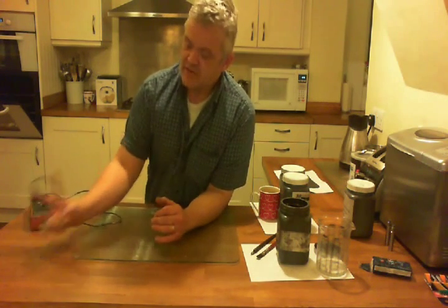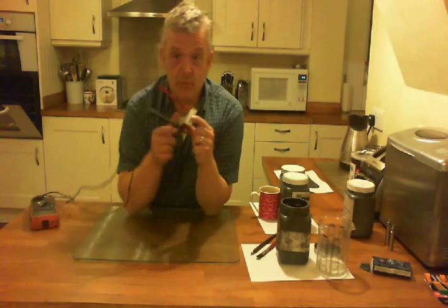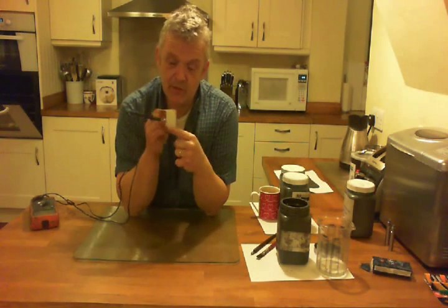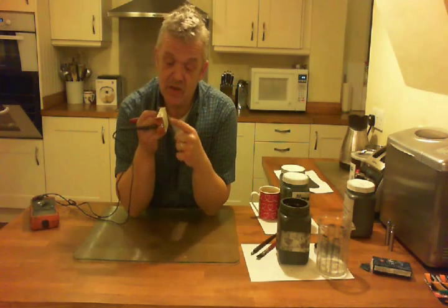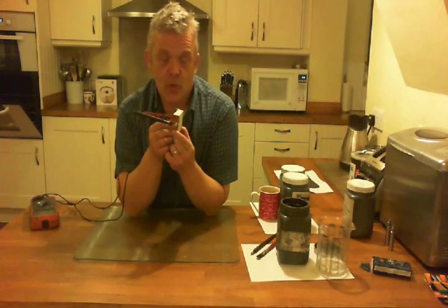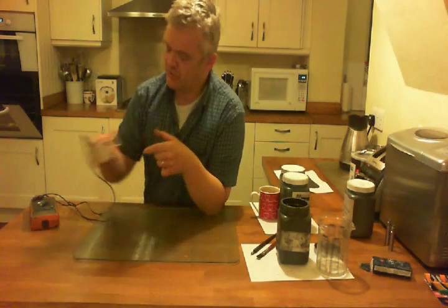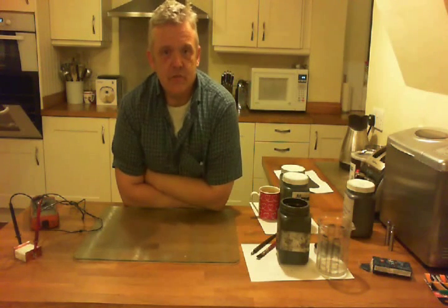The standard way of doing this is to construct a square probe — copper contacts held apart by a plastic block the same distance as they are in length. If I press that onto my sheet material, it measures directly the ohms per square sheet resistance. So if you want the resistance of a painted line ten centimetres long by one centimetre wide, it will be ten times the ohms per square measurement, because you're making up ten squares of one centimetre by one centimetre.